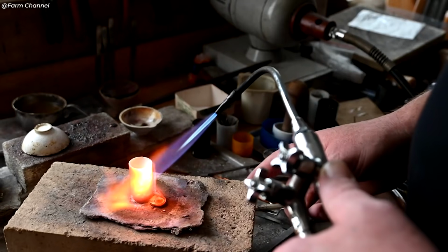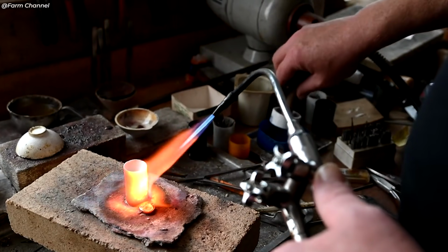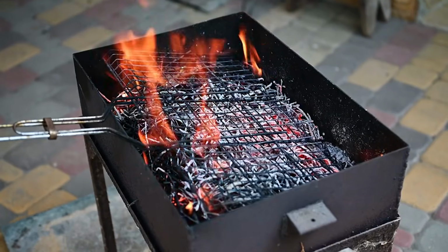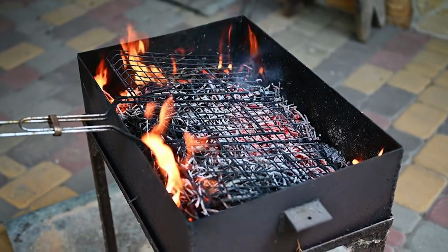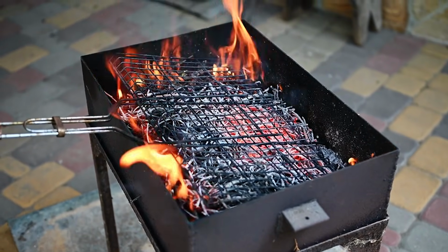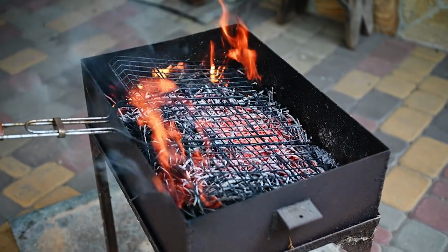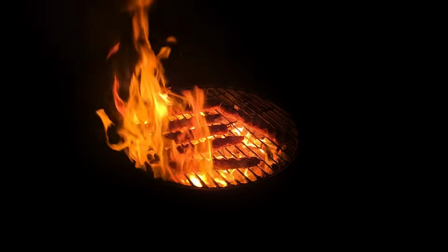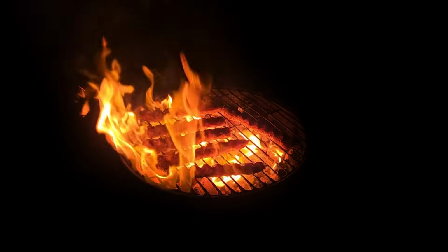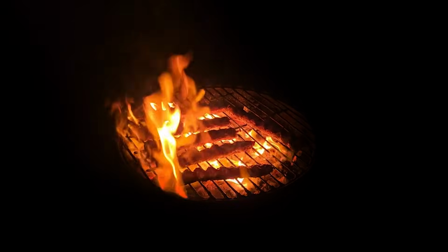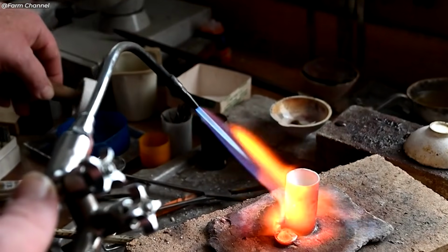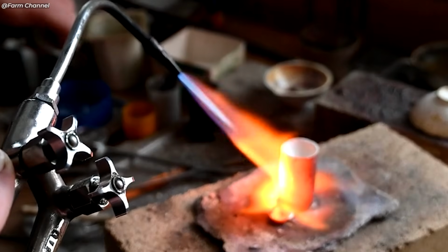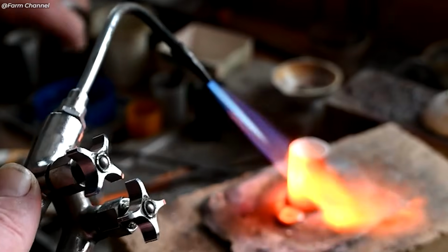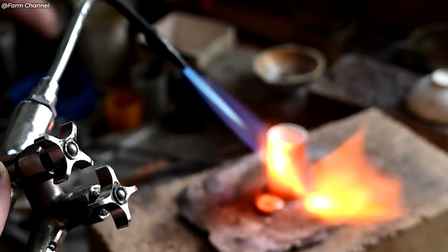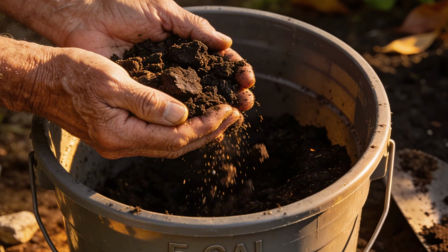Now here's the critical part: the heat treatment. Build a charcoal fire in a simple fire pit or even a barbecue grill. Use a hairdryer or a small blower aimed at the base to get the coals hot enough. You need the steel to reach that cherry red color, a medium red glow, visible in shade but not blinding bright. Hold the blade in the fire with long-handled tongs for about 5 to 7 minutes, turning it so it heats evenly. Once it is glowing an even cherry red, quench it quickly in a bucket of used motor oil or vegetable oil, not water.